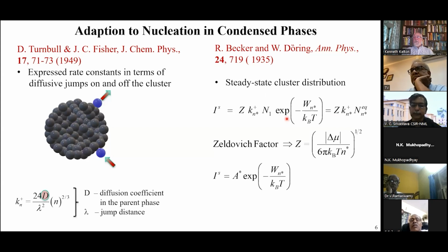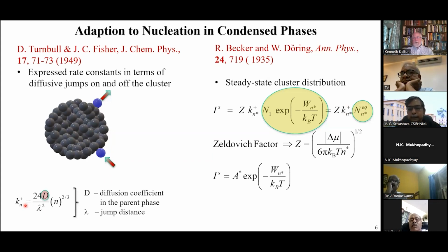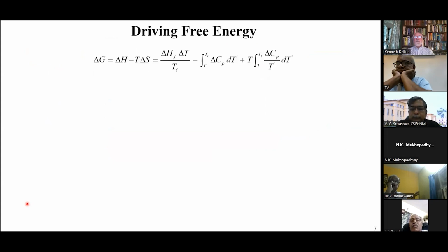It doesn't vary much. The forward rate constant, and then the Boltzmann factor term. So that means, if you look at this term, this is just the equilibrium concentration. So they said the steady state rate was equal to this factor Z multiplied by the forward rate constant multiplied by the equilibrium concentration. And if you go back to Turnbull-Fisher, that's where the forward rate constant is. So it seems like we now have everything together where we can describe the nucleation rate. And together, this is called the classical theory of nucleation as it's applied to a variety of different systems.